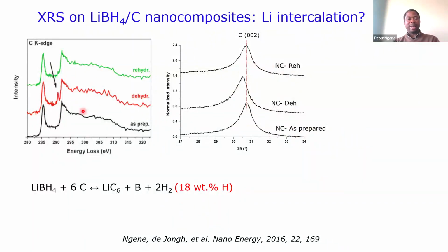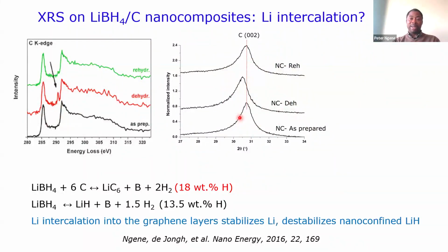So this thing that we observe with X-ray Raman scattering, we can see also from this. And with that, we actually look also at NMR, and we do see some things. But what we learned from this is that for the fact that this is reversible, this suggests that the lithium is intercalated in the graphene layers when we dissolve this material. And so, which means that this kind of reaction is going on, because we do know that the lithium can intercalate.